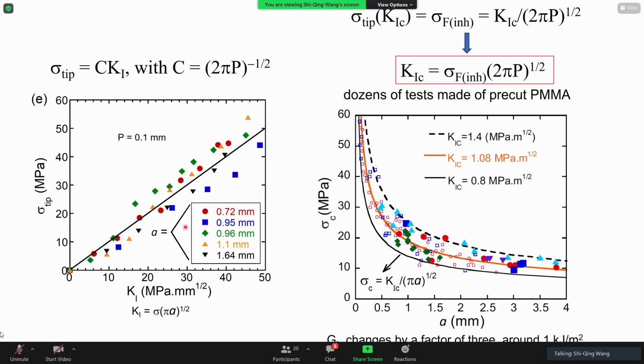By dimensional analysis, this means that the constant must involve some characteristic length, in this fashion, 1 over the square root of the length. In fact, this relationship holds all the way to the point of fracture. Moreover, this plot shows that at the fracture, the local tip stress has reached a level which is essentially comparable to what you see in an uncut sample. So we are starting to be able to claim that the inherent strength is actually not much different than the nominal strength.